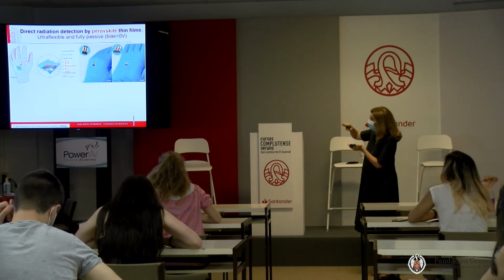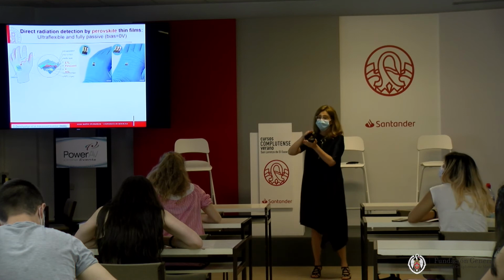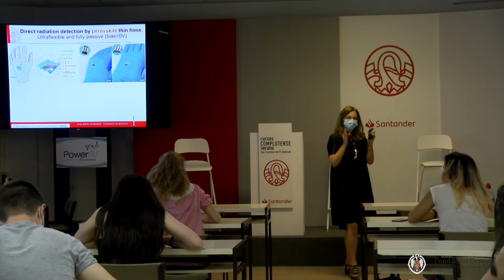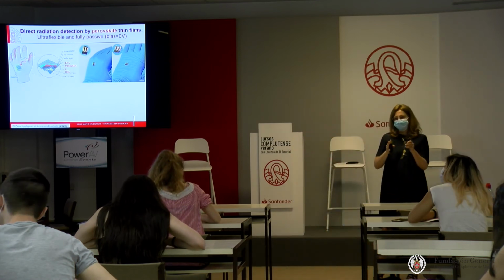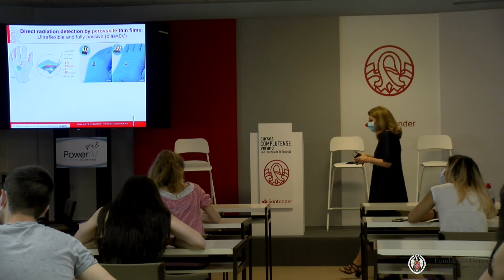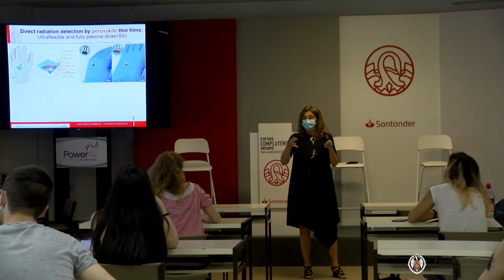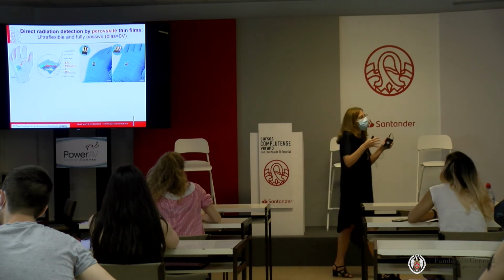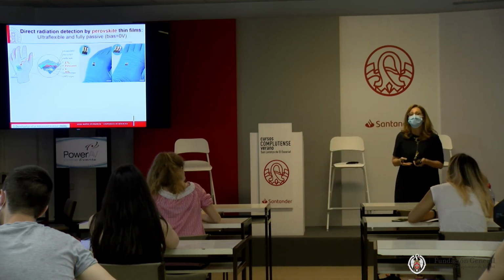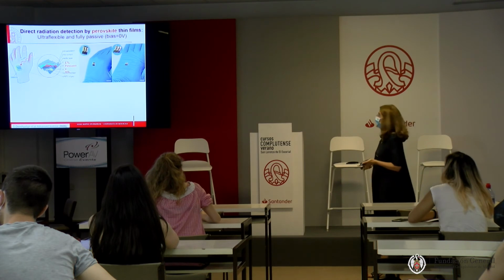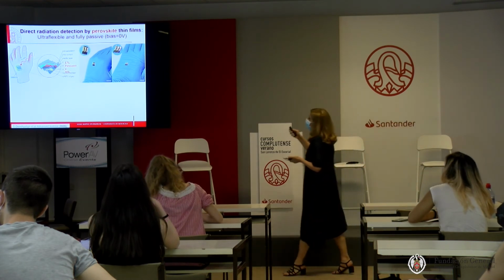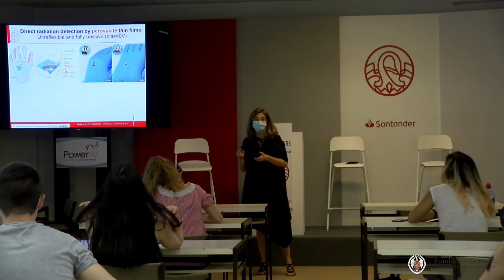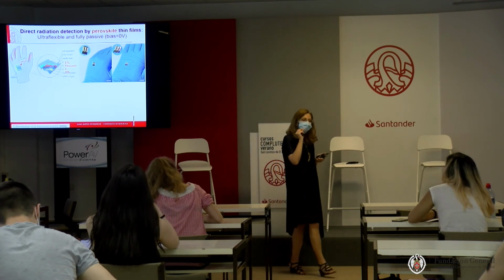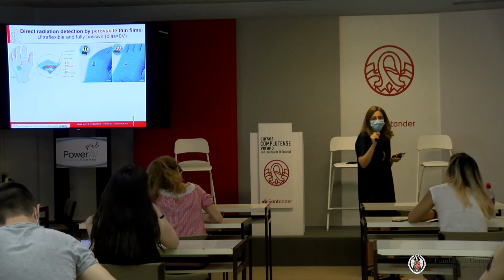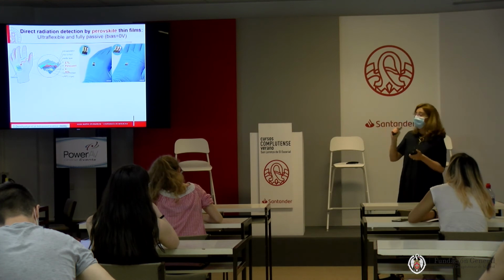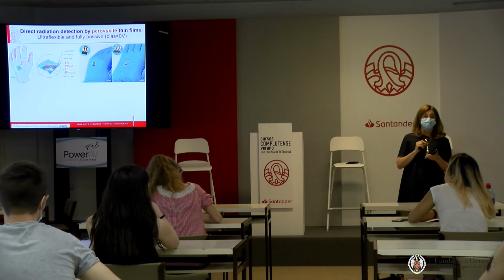Basically, here you see a structure where you have the perovskite in the middle and some layers on each side that help in creating an electric field capable of extracting the carriers that are generated, and at protecting the perovskite from degradation from external agents. Indeed, we can fabricate very thin and flexible devices because everything is really very, very small. The thickness of the active layer is still about 100 or 200 nanometers.